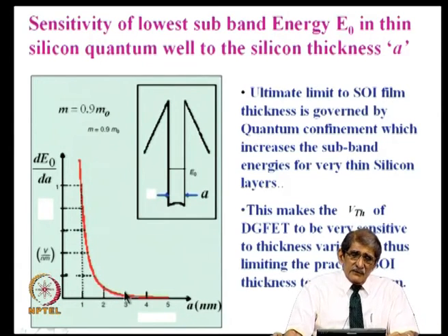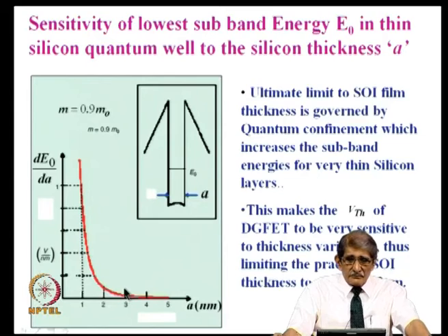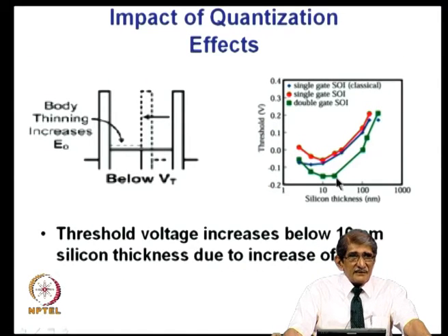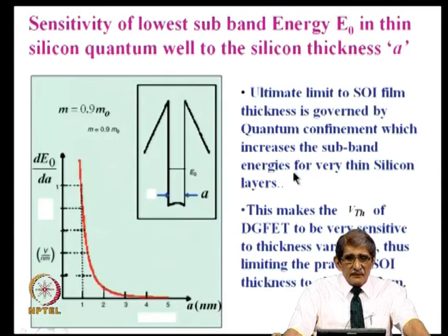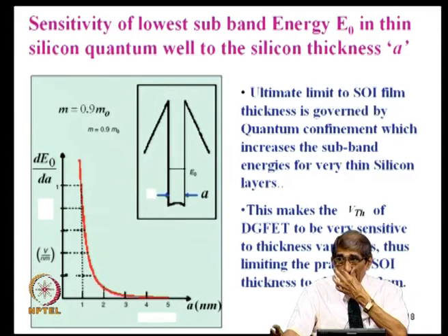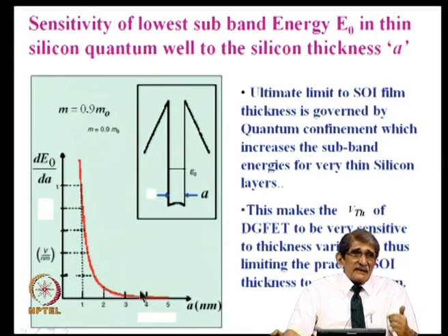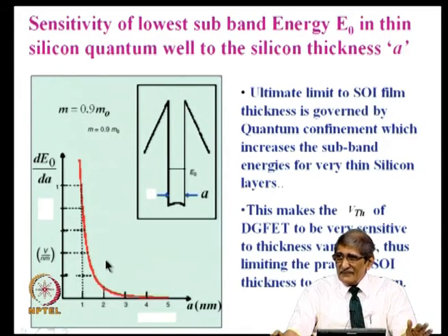More than that, see what we said is, keep on reducing the thickness, threshold voltage keeps on falling, that is good. But if you go to 3 nanometers, etcetera, because of this effect, threshold voltage will increase. You may not mind if it remains constant flat there, but it increases, it is bad news from two points of view. One, threshold voltage is high, means your supply voltage must be high. Second one, you go to 3 nanometer thin SOI layer. You know how hard it is to get 3 nanometer uniformly over the entire wafer,